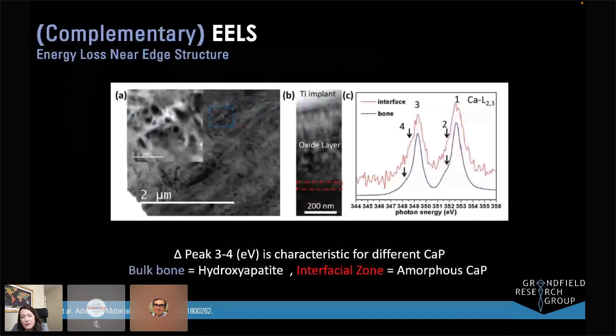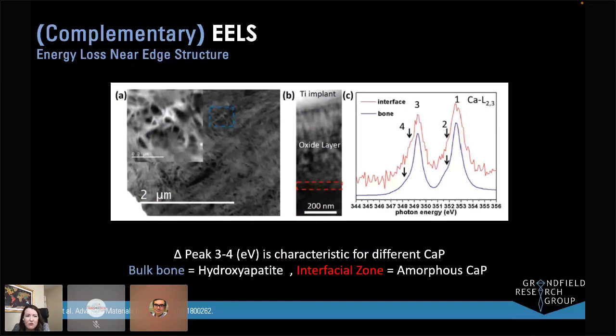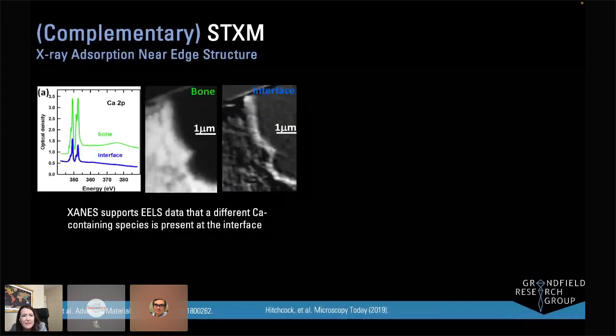We've looked at some other imaging and spectroscopy techniques to see what type of mineral could be inside the oxide layer versus further away. These techniques show that at the interfacial zone we likely have more of an amorphous calcium phosphate introduced inside the oxide layer, whereas further away from the interface we have the standard hydroxyapatite crystal. This work shows something quite similar, that we have a different calcium species at the interface.